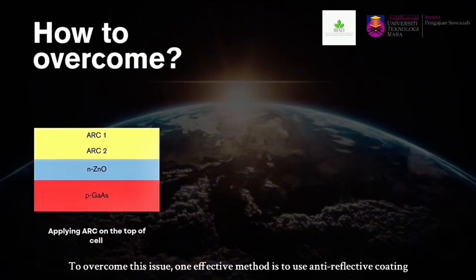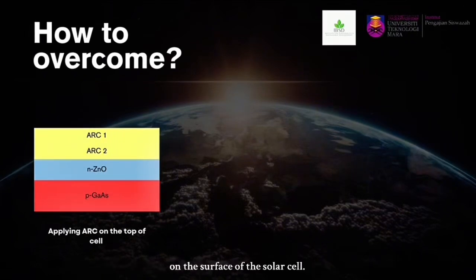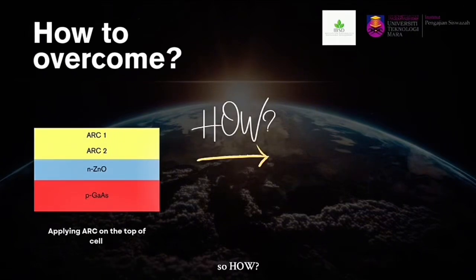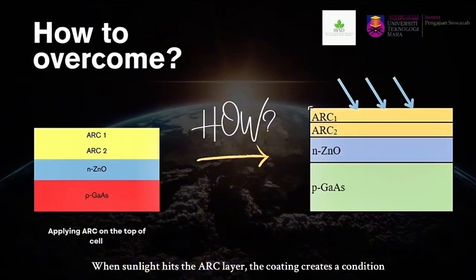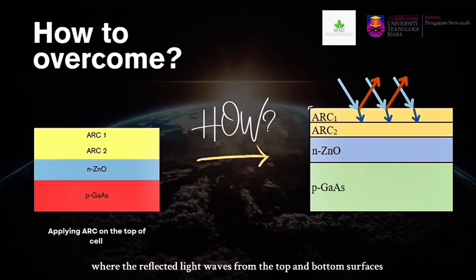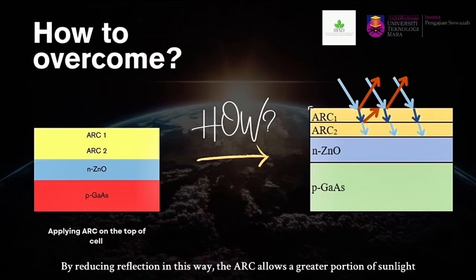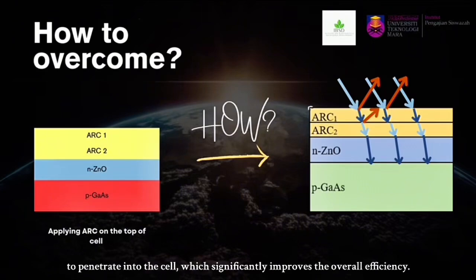To overcome this issue, one effective method is to use an anti-reflective coating on the surface of the solar cell. So how? When sunlight hits the ARC layer, the coating creates a condition where the reflected light waves from the top and bottom surfaces interfere with each other and cancel out. This phenomenon is called destructive interference. By reducing reflection in this way, the ARC allows a greater portion of sunlight to penetrate into the cell, which significantly improves the overall efficiency.